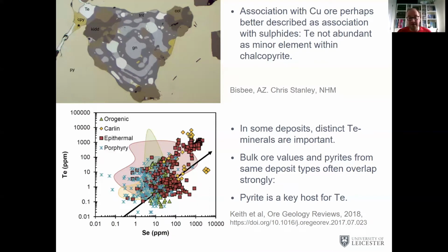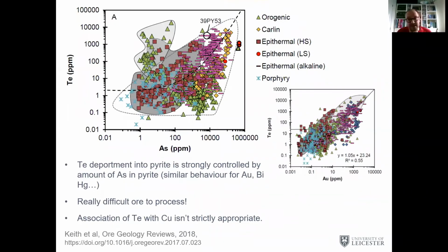In a lot of locations, what we find is that pyrite is actually the most abundant and important host for tellurium. We find that bulk ore values and pyrite values strongly overlap in terms of concentration. In other words, the tellurium content of pyrite is basically the proxy for the tellurium content of the rocks. So pyrite is a key part of it. Pyrite can be quite a dirty mineral in terms of its trace element record, and in the age of laser ablation ICP-MS we're getting a much better handle on this, and we're seeing that pyrite can be an important part of controlling the trace metal assemblage of an ore.